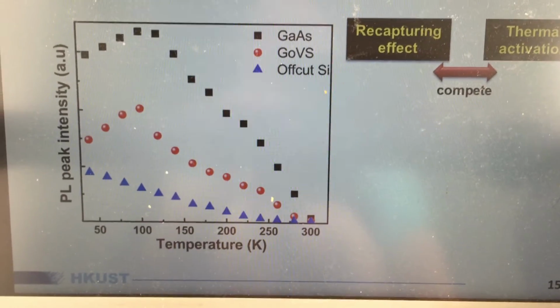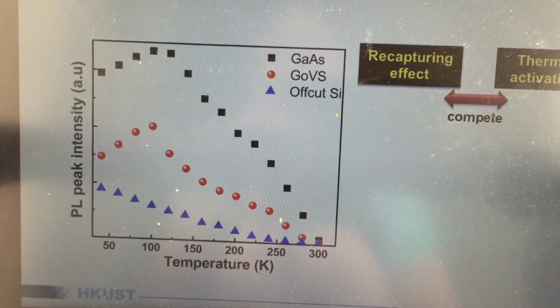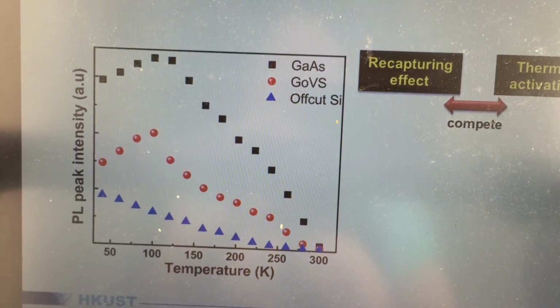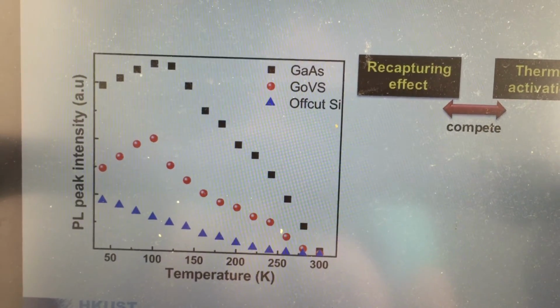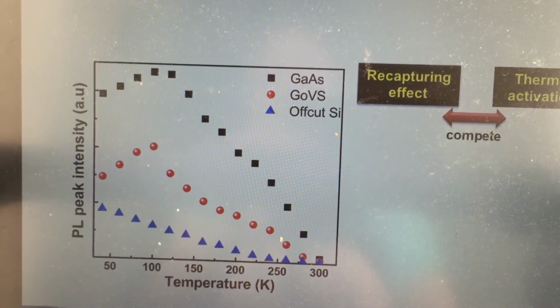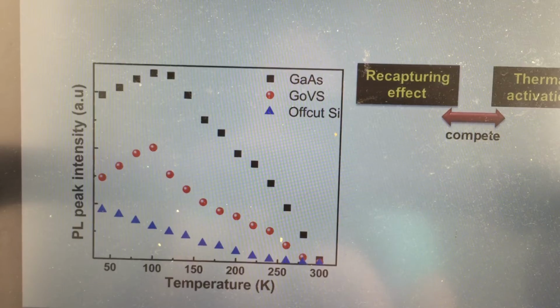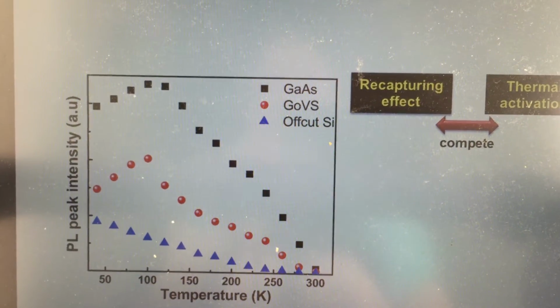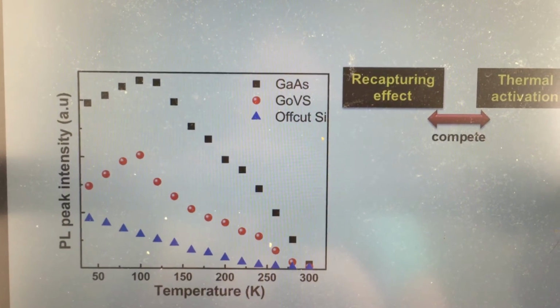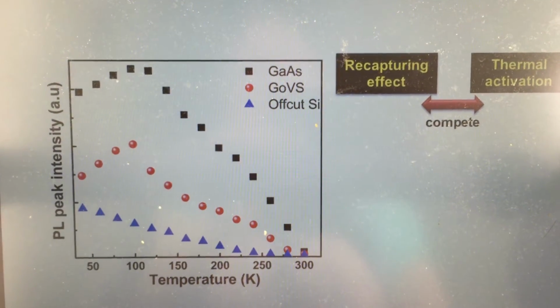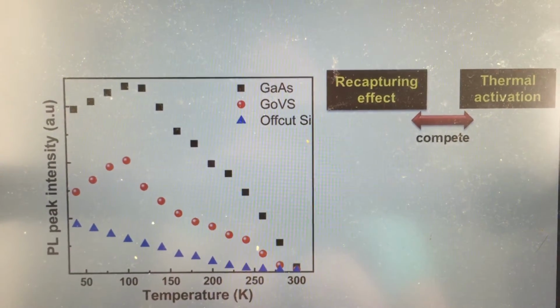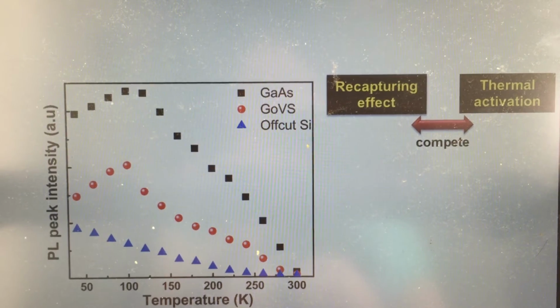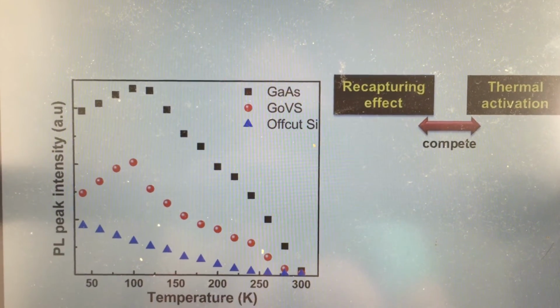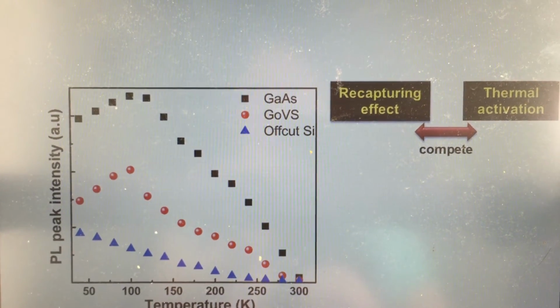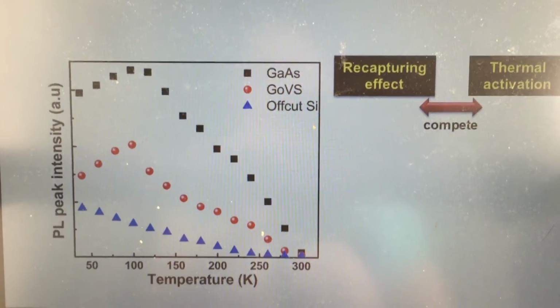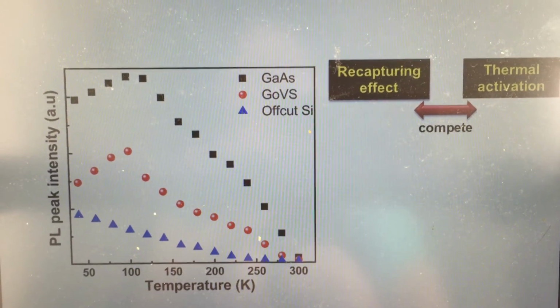We then track how the PL peak intensity changes with temperature. We know that there are always two effects competing with each other over the whole temperature range. The recapturing effect refers to photocarriers in the wetting layer getting a chance to be recaptured by the quantum dots again. This leads to an increase in PL intensity and is the dominating factor in the low temperature range. The thermal activation effect, on the contrary, means the photocarriers captured by the quantum dots can get a chance to be thermally activated out of the quantum dots. This leads to a decrease in PL intensity and is the dominating factor in the high temperature range.